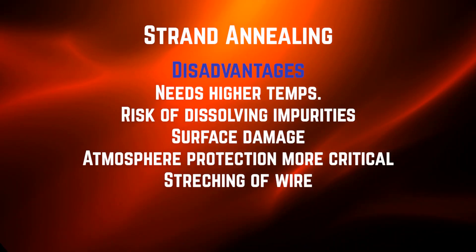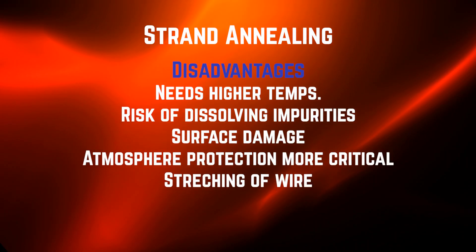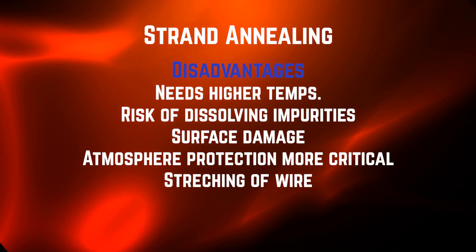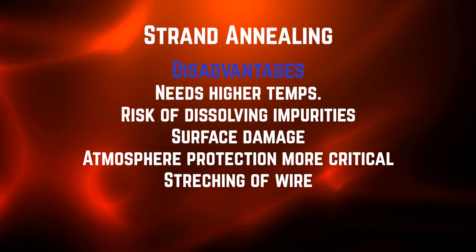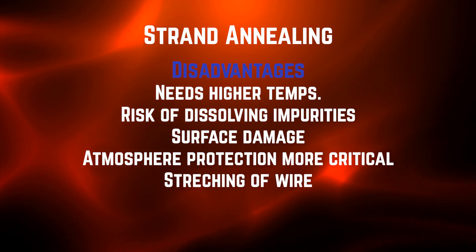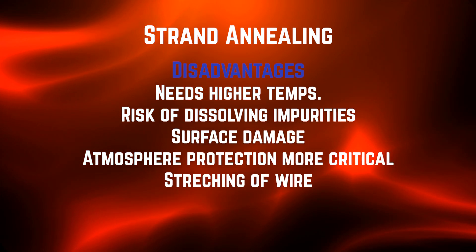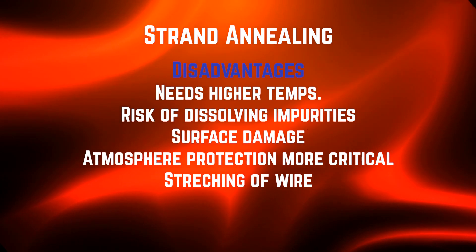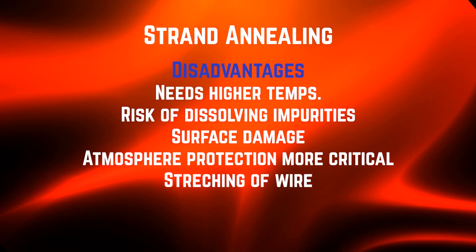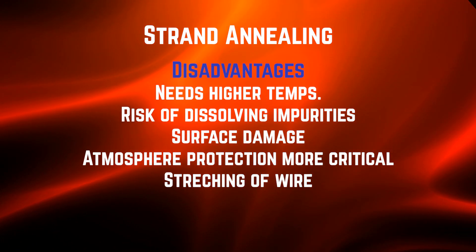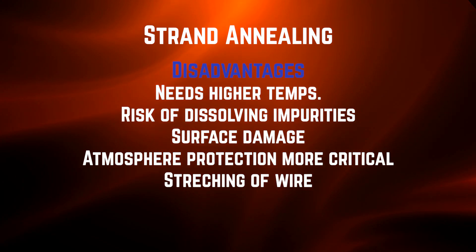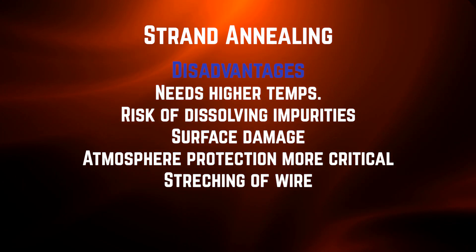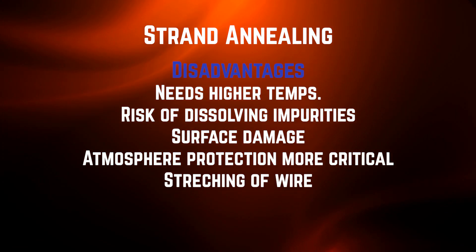The only problem with strand annealing is because the time is so short, you have to go to much higher temperatures, and you can do some surface damage because the wire is so soft. If you're not careful and you have some tension on a wire, you can stretch it. Also, you have the risk of dissolving some of the impurities, which can have a negative effect.